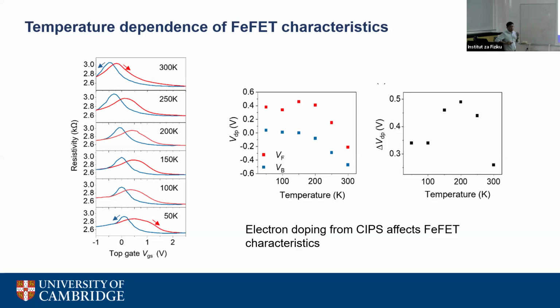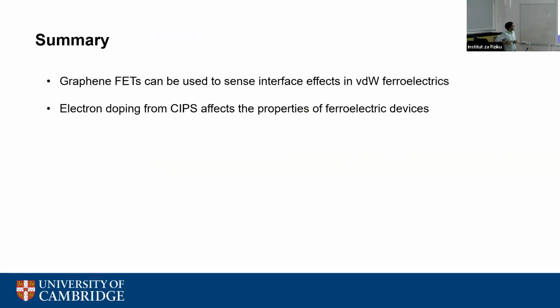So we feel graphene FETs can act as a sensor to understand ferroelectric properties of not just CIPS, but also a lot of other ferroelectrics which are emerging, such as the moiré ferroelectrics out of twisted TMDs and twisted boron nitride. It's an interesting way to understand what is happening at the interface. In this case, it is due to copper ions. In other cases, it could be due to moiré potentials that are generated when you twist these heterostructures. So to summarize, we have used graphene FETs to sense interface effects in van der Waals ferroelectrics. And we show that when you put CIPS on graphene, it can really electron dope graphene,